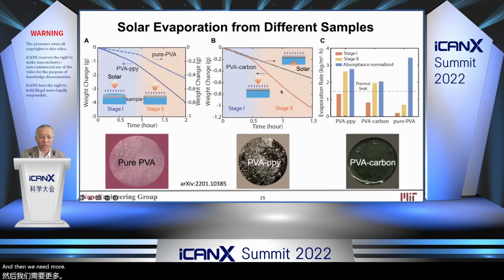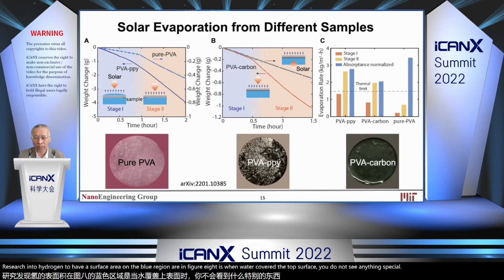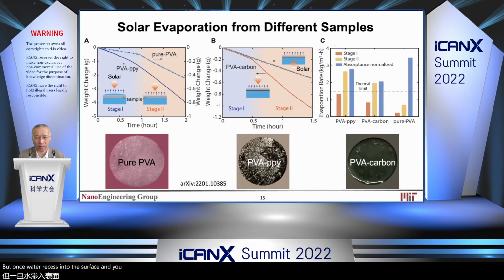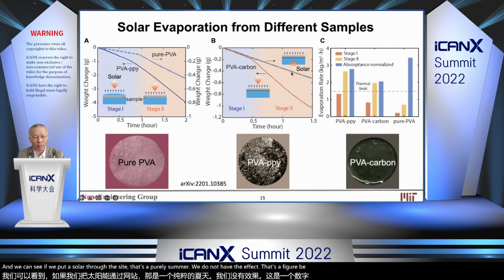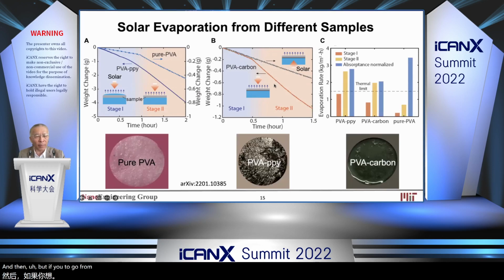And then we did more evaporation experiments, and you can see, even without any absorber, with pure hydrogel, in figure A, under light, the evaporation rate suddenly increases. You need to have the water recess into the hydrogel to have a surface area. The blue region in figure A is when water covers the top surface, and you do not see anything special, but once water recesses into the surface and more area is exposed, you have a suddenly increased rate. This also explained Professor Yu's previous experiment using pure hydrogel with a carbon paper, where if we put the solar from the backside, that's purely thermal, we do not have that effect. That's figure B in the middle. But if you go from the top, it has that effect.